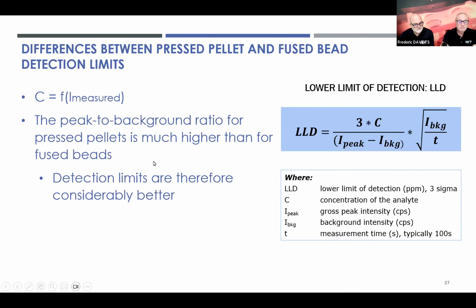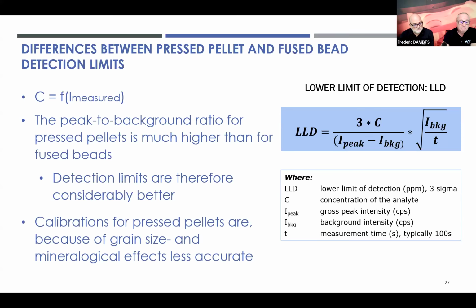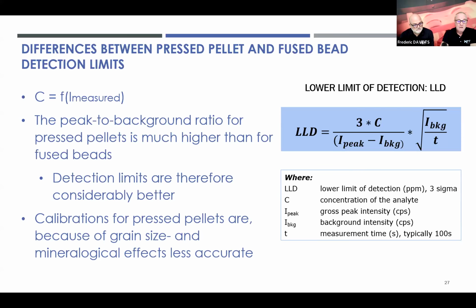Now, the peak to background ratio for pressed pellets is much higher than for fused beads, which we will also see on the next slide. So therefore, the detection limits are also considerably better. Now, calibrations for pressed pellets, on the other hand, are a bit less good than for fused beads, and that's because of grain size and mineralogical effects.